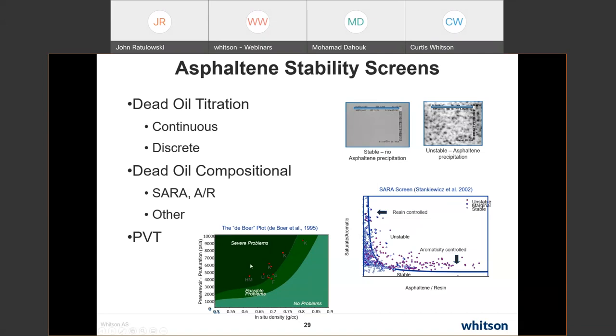It doesn't look at the oil at all. It just looks at the potential loss in stability of the system. So it really is looking at something very different. Now this screen got a lot of kind of bad press, I think, because oftentimes it would predict a problem where you saw no problem. That's because they weren't really looking at the asphaltene or the liquid composition at all. They were just looking at the overall PVT properties. So you could have something that fell in the severe problem region that actually had no asphaltene in the system. So you really need to use these dead oil titrations and compositional screens in conjunction with the PVT screen.